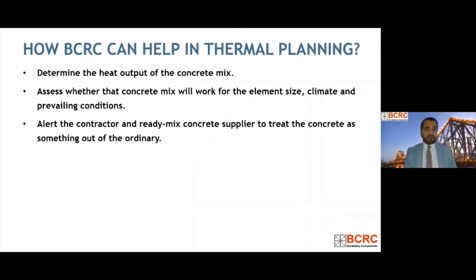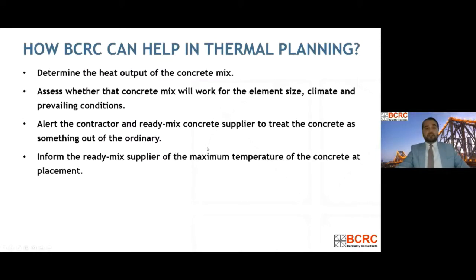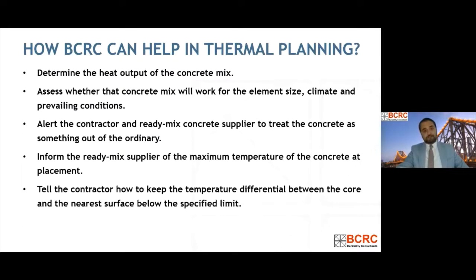We can alert the contractor or concrete supplier to treat the concrete as something out of the ordinary, if it is required. We can also inform the ready-mix concrete supplier about the maximum temperature of concrete at placement for that particular element. Tell the contractor how to keep the temperature differential between the core and the nearest surface within the specified limit, and how to lower the risk of cracking.